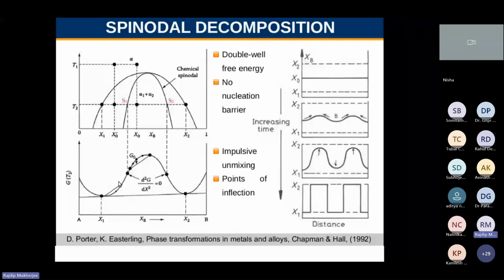So when we extract the free energy for iron chromium or iron copper alloy, we will get a similar free energy curve for those systems. So these are called double well free energy curves. Inside the spinodal line, there will be no nucleation barrier. Outside the spinodal line, in a two-phase region, there will be nucleation and growth.